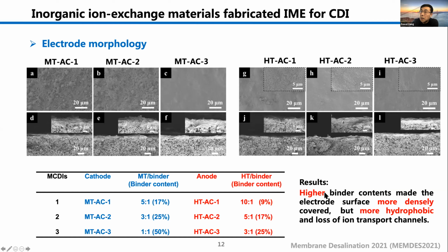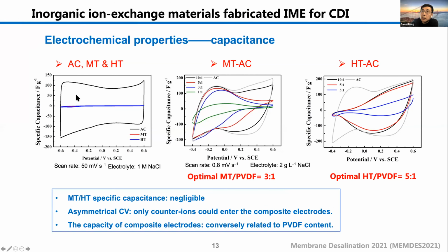And the result is that the higher binder content made the electrode surface more densely covered and more smooth, but more hydrophobic, with a loss of ion transport channels. The ion exchange material's intrinsic capacity is negligible. But when coating on AC, you could see that only the counter ion could enter the composite electrode. And the capacity of this composite electrode is inversely related to PVDF content. But finally, we got the optimal ratio. For the cathode it is about 3:1, and for the anode about 5:1. It's about 25% of binder and 17% of binder.